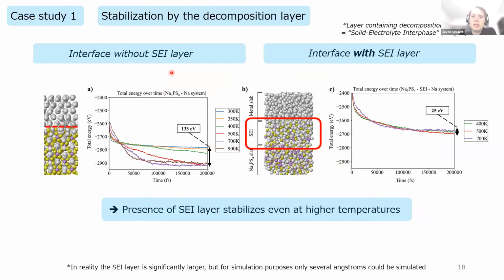Now, in batteries, we of course always have reactions. It will be inevitable. But one of the ways in which we can get these systems to remain stable is if the decomposition products provide stability, passivation, so that they don't let the reactions escalate further. And so what we did is we took the decomposition products from the 400 Kelvin output, and put them in between a new metal slab of sodium and the solid state electrolyte. And we call this the SEI layer, a solid electrolyte interphase. It's a layer which contains these decomposition products.